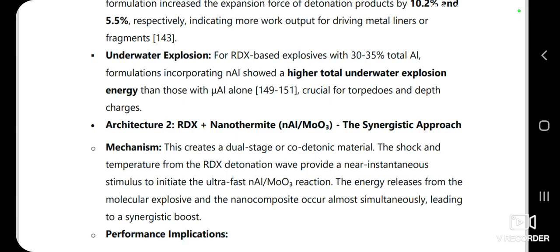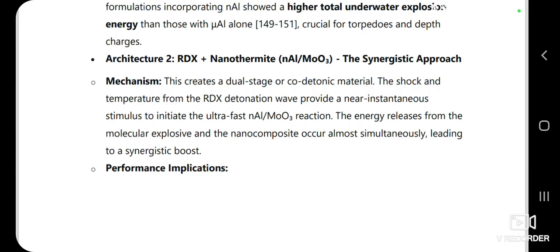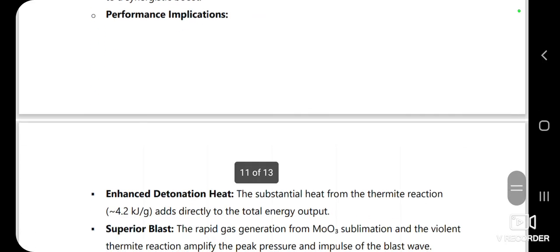Next, Architecture 2, we study RDX plus nanothermite, nanoaluminium and molybdenum trioxide. That is a synergistic approach. This mechanism creates a dual-stage or co-detonic material. It's not sequential, it's co-detonic. The shock and heat from RDX detonation provide the perfect instantaneous trigger for the ultra-fast nanothermite reaction. The energy is released simultaneously and amplifying each other. The energy release from a molecular explosive and nanocomposite occurs almost simultaneously, leading to the synergistic boost.